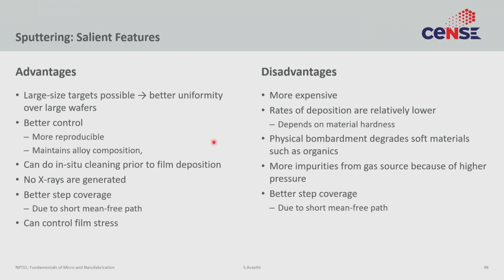The disadvantages are that it's a much more expensive process. The rates of deposition are relatively lower. Evaporation can be very, very high. Physical bombardment tends to degrade soft materials. So if you're trying to deposit on top of, say, an organic semiconductor, sputtering creates a lot of damage. Evaporation does not. More impurities, because you tend to function at higher pressures, which basically means that the incorporation of argon and other impurities into the film tends to be higher. And better step coverage basically means you don't have very sharp profiles, which is a problem for liftoff, as we shall discuss a few lectures later.